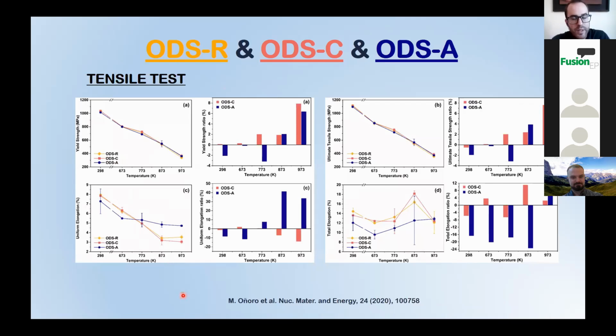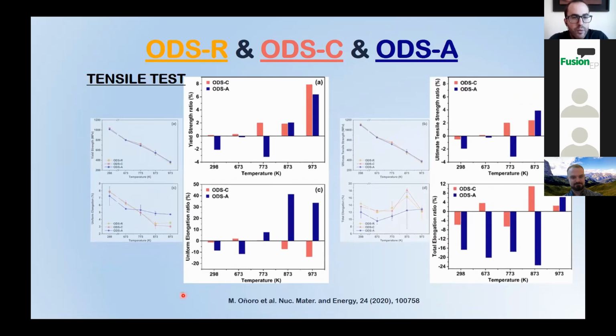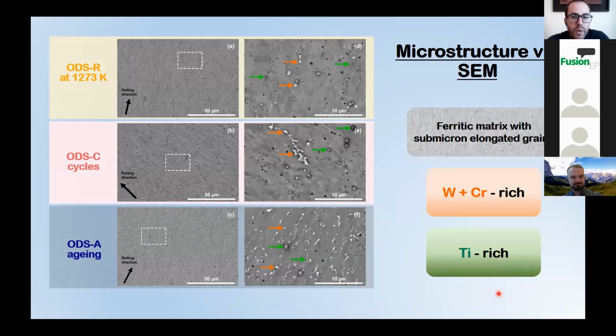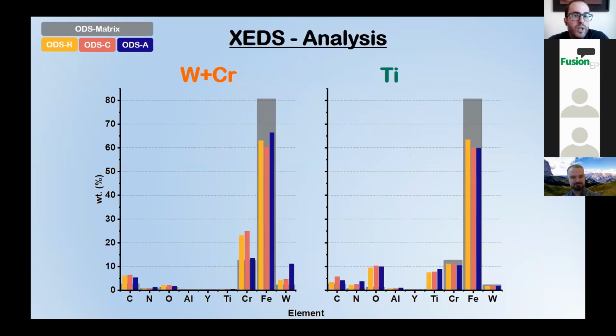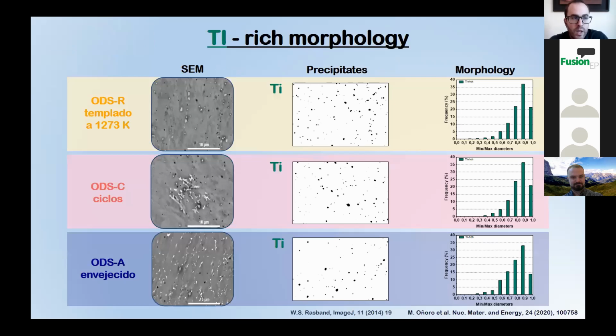We also completed the tensile test characterization. When comparing ODSC and ODSA with the annealing results, the bar diagrams, the strength parameters showed an improvement at high temperatures, while aging, ODSA, produced a general loss of the elongation values. Scanning electron microscopy revealed a stable matrix of submicron elongated grains following the HCR direction. Furthermore, two different secondary phases were identified along the three different samples, a tungsten-chromium-rich precipitate in orange and a titanium-rich one in green. A semi-quantitative analysis of the chemical composition showed on the aged samples a reduction of chromium together with a tungsten increment on tungsten-chromium-rich precipitates. This could be a hint of Laves phase formation. Moreover, this analysis emphasized the stable composition of titanium on titanium-rich precipitates.